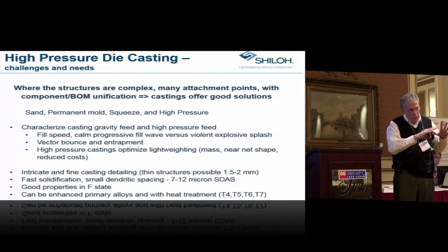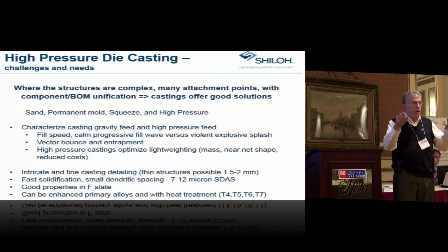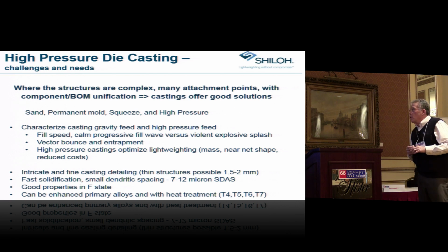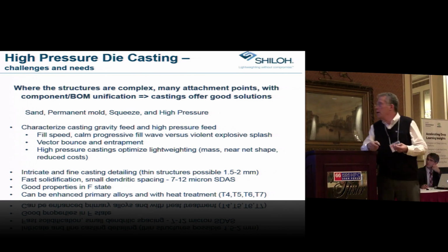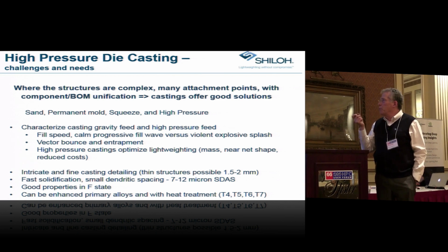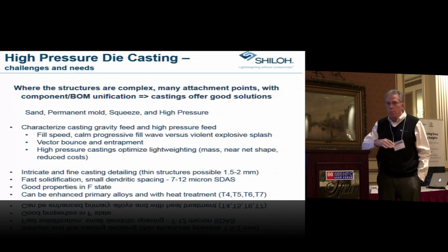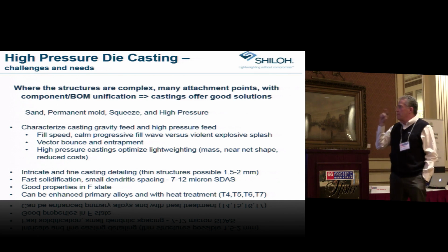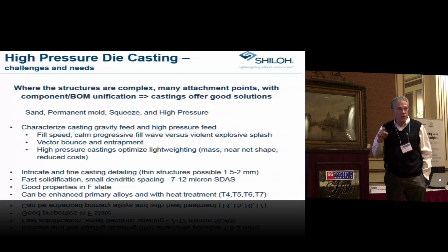If we're looking at the casting, there are the older casting methods which are gravity fed, which are a lot simpler to model because they're moving at a very slow fill rate. But the area that offers the greatest opportunity is the high pressure side, which has the greatest challenges on the modeling. High pressure has a very fast fill speed rather than a calm progressive fill. It has violent splash parameters on the inside of the die. It's got bounce, it's got entrapment, and that's an area where a lot of the casting optimizing and lightweighting is having a big impact. You've got fine details, might be 1.5 or 2 or 2.5 millimeter wall sections. They're big castings, filling out over big areas.